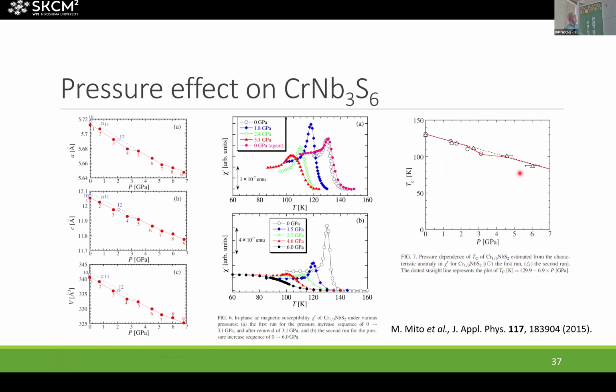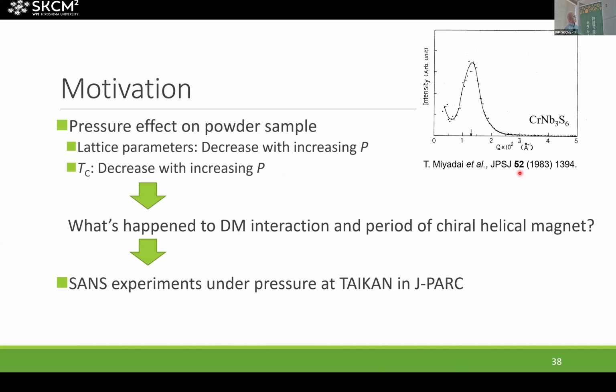Ito sensei studied the pressure effect of these materials using a powder sample, from AC magnetization and magnetization measurement. The lattice parameter and transition temperature decrease with increasing applied pressure. Then we would like to know what happens with the Dzyaloshinskii-Moriya interaction and the period in the chiral helical magnet.